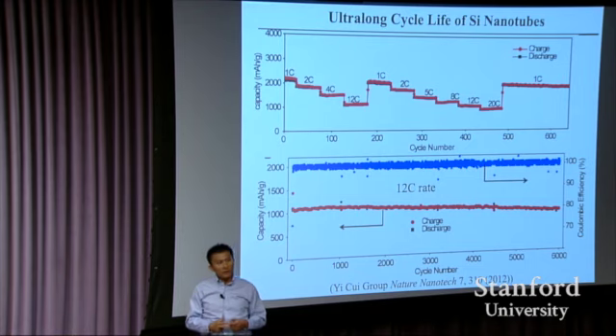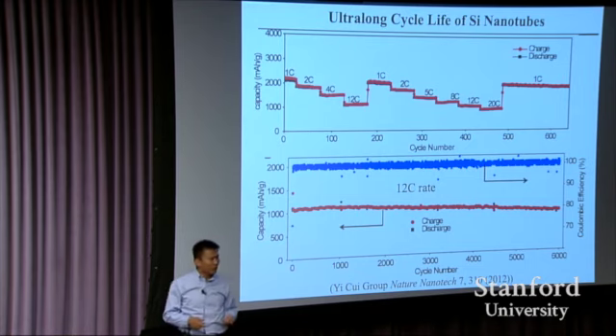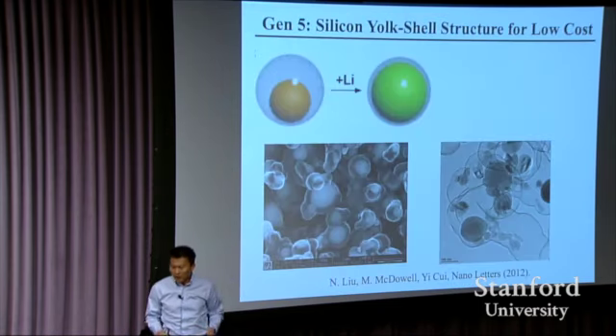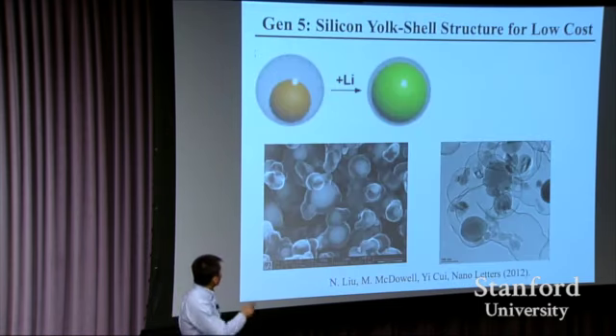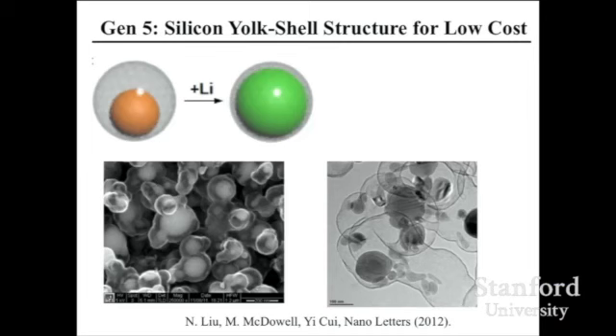Huge capacity, but big structure change and volume expansion. Now how do you make them low cost, right? This is a high cost process using chemical vapor deposition. And this comes to our generation 5. Silicon nanoparticles can be made at a relatively low cost compared to the gas phase synthesis. We actually made this a yolk-shell structure. This is just like an egg. And this is the yolk, this is the shell, this empty space right there.